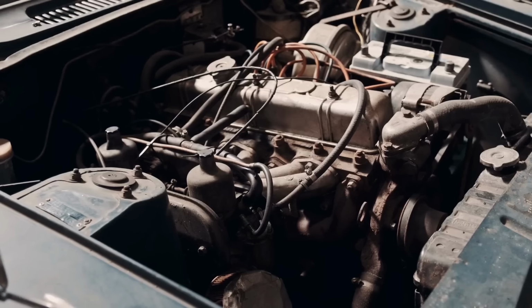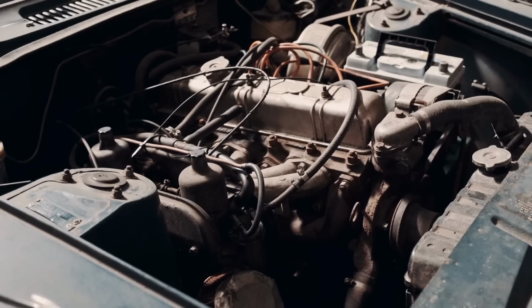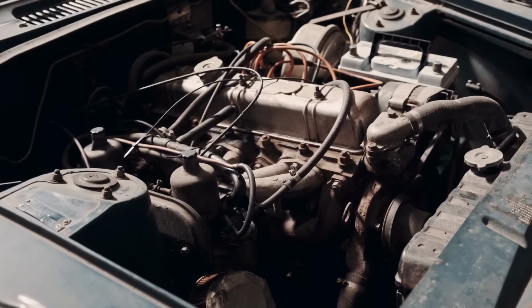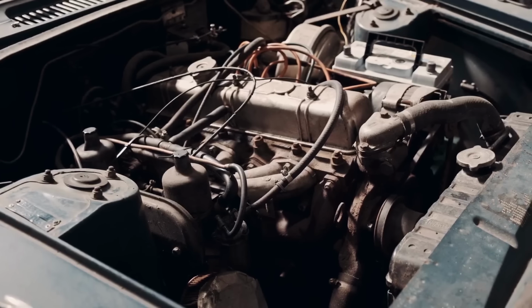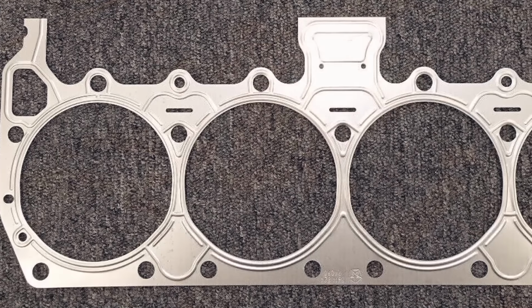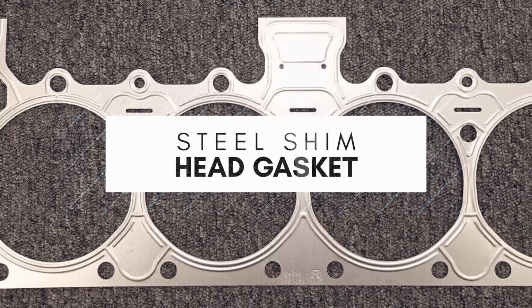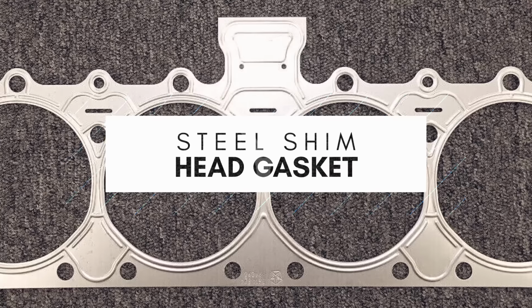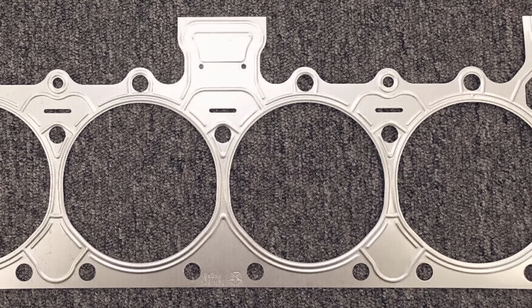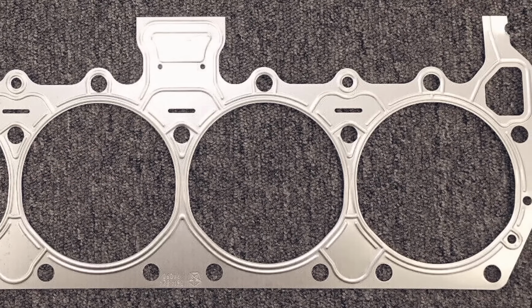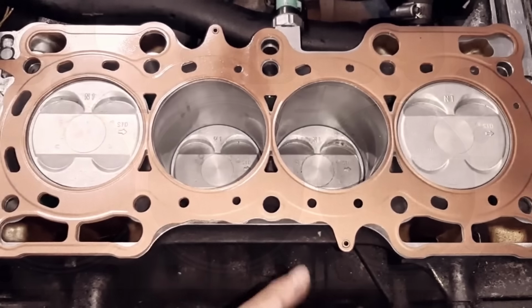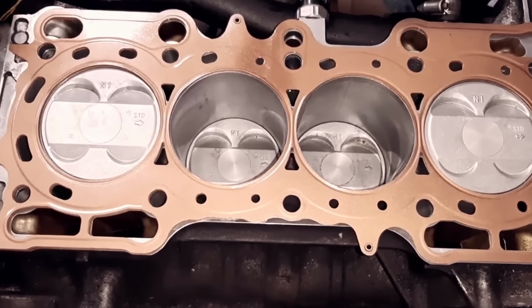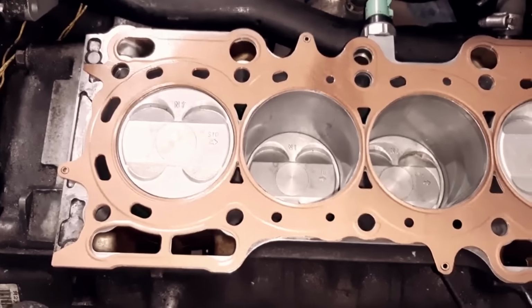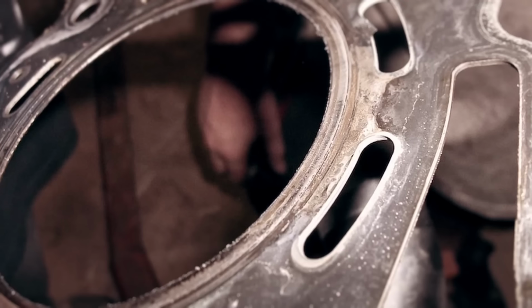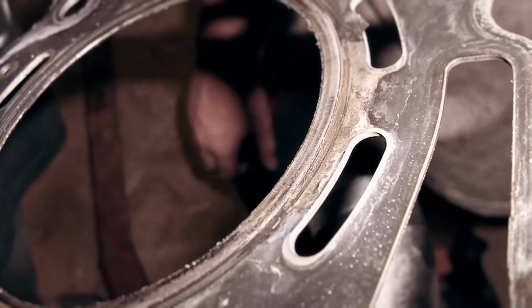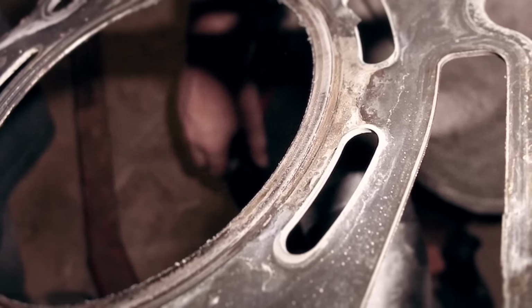As the automotive industry began to flourish in the 1920s and 30s, less costly, mass-production-friendly head gasket designs were explored. One durable yet relatively inexpensive option was the steel shim head gasket. While extremely resilient and less susceptible to seal loss from heat cycling when compared to copper, steel shim head gaskets required a copper coating to properly seal against surface imperfections. However, they did suffer from corrosion issues, especially from coolant flow that would ultimately degrade the gasket's ability to seal over time.